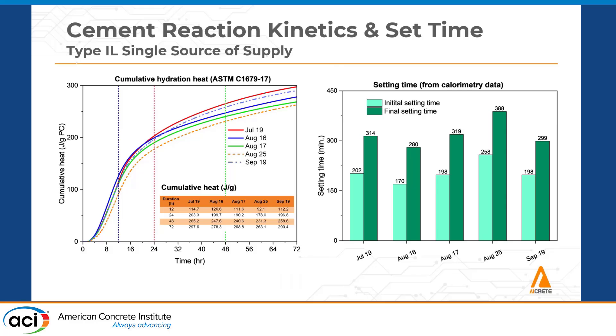This one is for the hydration. You can see the difference between the different lines from July through September, as far as the range in performance. As well as the difference in set time — there was a difference of almost about an hour and a half between the two that they were seeing.